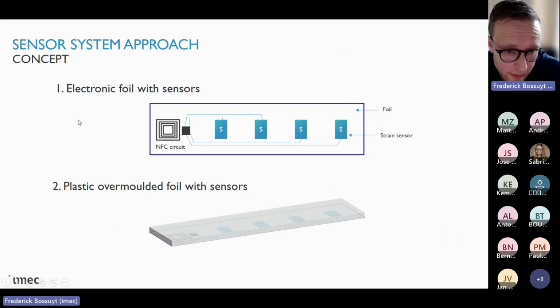So the idea is that based on the technologies we have, we make an electronic foil with the sensors on it. So in this case, strain sensors, which are applied on a foil, and we have a small amount of electronics that can read out the sensors, and that we can wirelessly transmit that sensor information to an external device which is in close contact with the plastic part. So if we have these foils, then we overmold the foil, so that we introduce such a sensing foil during the overmolding or the injection molding process of the device.